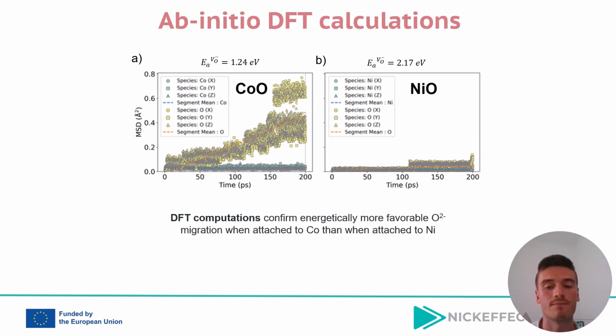This was the reason why magnetoionics was faster, or more energy efficient, in cobalt monoxide than in nickel monoxide, which justifies why the general magnetoionic behavior of the most cobalt-rich disks is better than in the most nickel-rich ones.